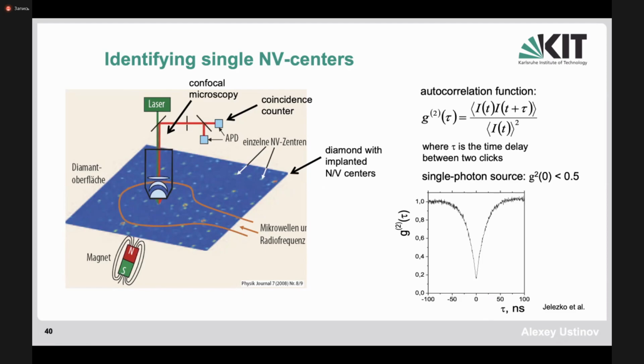However, if the delay is longer than a particular time, which is associated with the propagation path and also the intensity of the source, then the function actually goes to 1, and there will be independent, basically, clicks of those detectors. So single photon source actually can be recognized if this autocorrelation function squared is actually smaller than 1/2. And this is really the real data from the paper of Fedor Jelezko many years ago, showing that this is really a single photon source fluorescent from atomic scale defect.